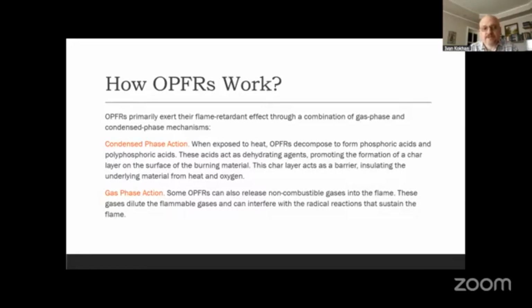mechanisms. Condensed phase action: when exposed to heat, OPFR decompose to form phosphoric acid and polyphosphoric acid. These acids act as dehydrating agents, promoting the formation of a char layer on the surface of the burning material. This char layer acts as a barrier, insulating the underlying material from heat and oxygen. Gas phase action: some OPFR can also release non-combustible gases into the flame. These gases dilute the flammable gases and can interfere with the radical reactions that sustain the flame.